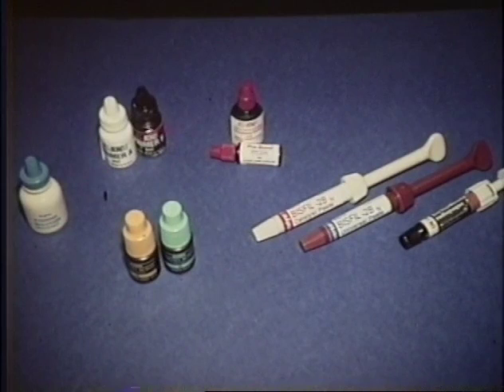All-Bond primer A and B in a wet field, not a dry one. This you leave wet, and by the way, don't ever, ever let it dry out between etching and priming, because if you let it dry in here, the All-Bond is almost worthless. You get sensitivity. You cannot remoisten a dried tooth. It cannot be done. It will not restore. It will not go back to its original state.